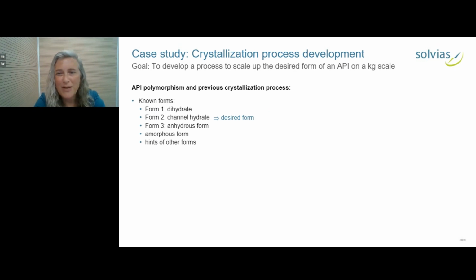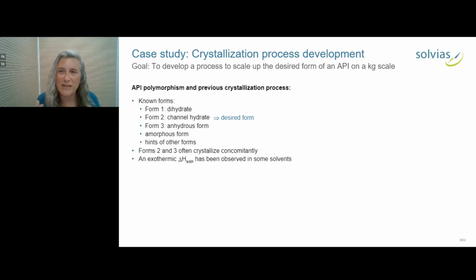And here the customer came to us after having already done a fair amount of work. They knew a bit about the polymorphism, and what they found was form 2, which was a channel hydrate, and form 3, which was an anhydrous form, often crystallized concomitantly. So they often got mixtures of the 2. What was also interesting was they noted an exothermic enthalpy of solution, heat of solution. So in some solvent systems, you actually had a lower solubility as you raise the temperature rather than a higher, which means instead of doing a cooling crystallization, you would do a heating crystallization.